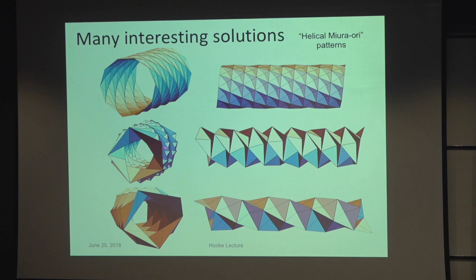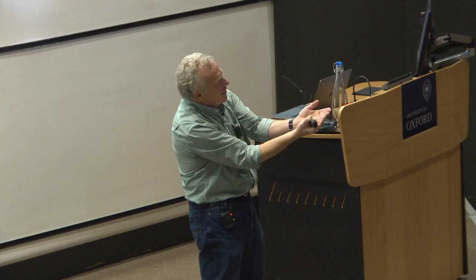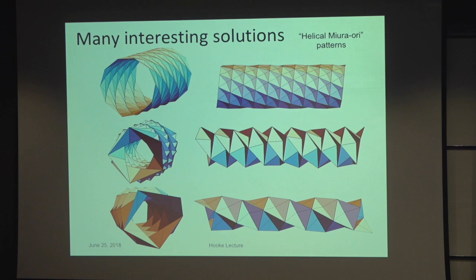This is one, for example, where the thing is folded, and then you fold it a little bit more, and you get this structure here. But you can imagine, as I said, you apply these group elements, you're building up this structure. When you get around the other side, of course, they may not meet. And so there's additional conditions. And actually, they're quite restrictive, so I won't go into detail.